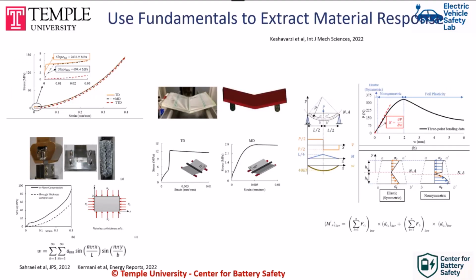So for the through thickness, it is easy. We just calculate that from through thickness test. For the in-plane loading, we need to understand what is the buckling strength of the foil. And then once we know the buckling strength, the behavior after that is very similar to the through thickness. So it's like shifting the curve by buckling strength. And then the tensile behavior is one of the things that is harder to calibrate because you cannot just get all of these layers and apply tension.